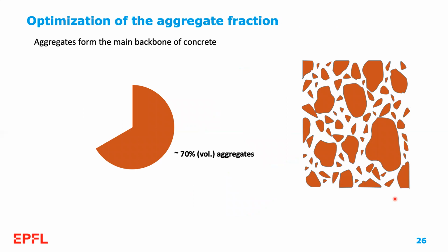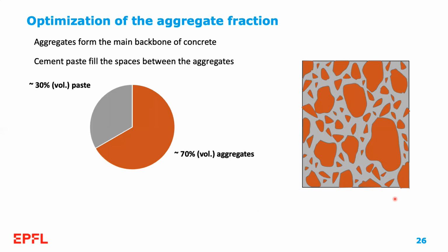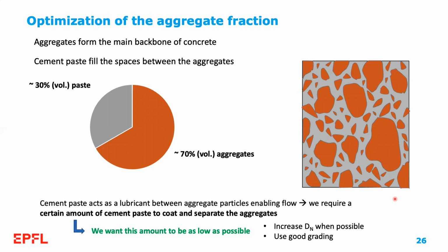In terms of aggregates, we need to realize that aggregates constitute about 70% by volume of our concrete. So our concrete, volumetrically speaking, is mostly aggregates, and the cement paste basically fills the spaces between these aggregates. We need the cement paste to coat the surface of the aggregates because it acts as a lubricant between them. And this is what enables flow at the fresh state of concrete.